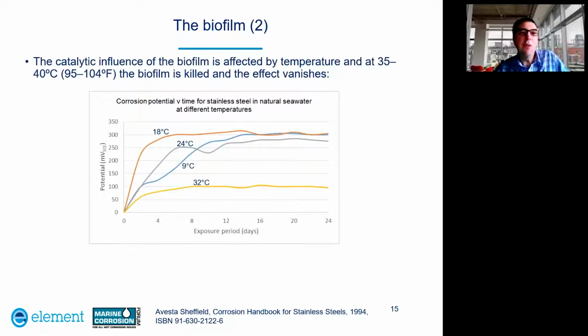So the catalytic influence of the biofilm is affected by temperature, and at 35 to 40 degrees the biofilm is killed and the effect vanishes. And this is illustrated by this graph, which shows that at the temperatures of 9 degrees, 24 degrees, 18 degrees, you get the ennoblement of the stainless steel up to about 300 millivolts due to the biofilm, whereas at the higher temperature you only get a small effect, and at an even higher temperature you get a very negligible effect on any potential increase.